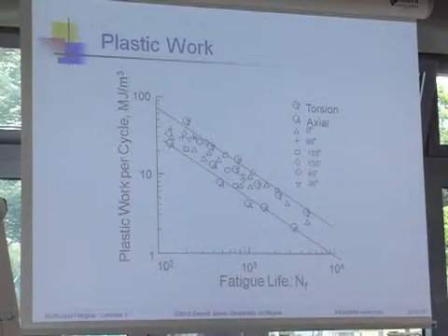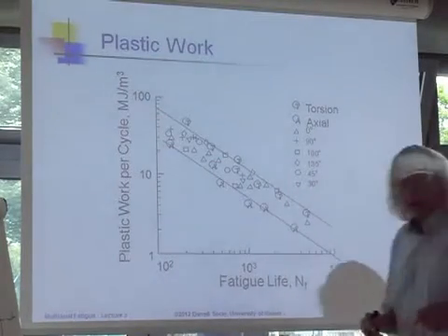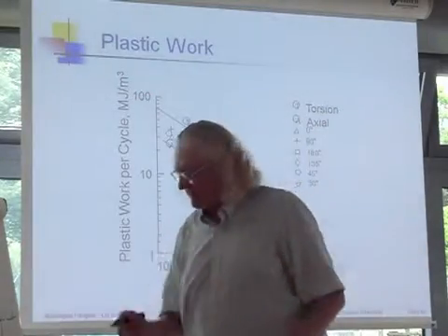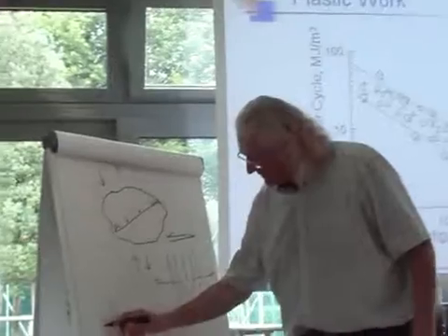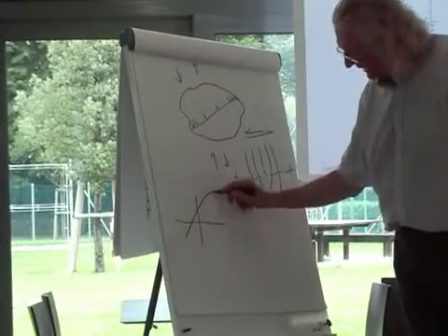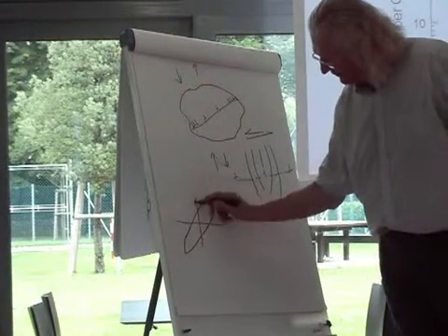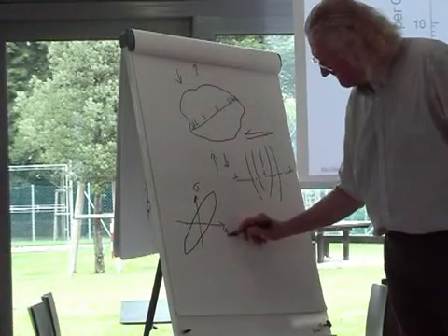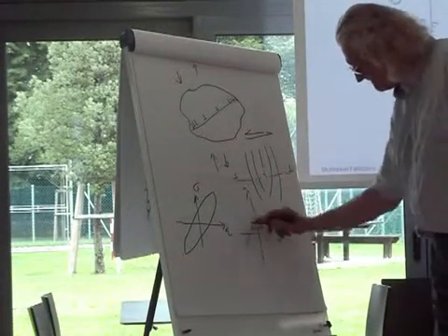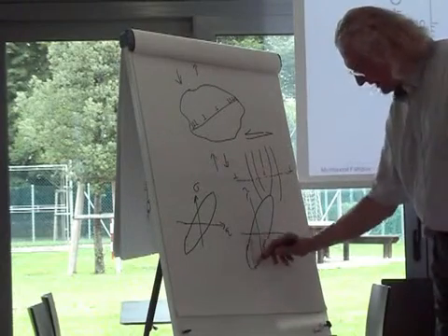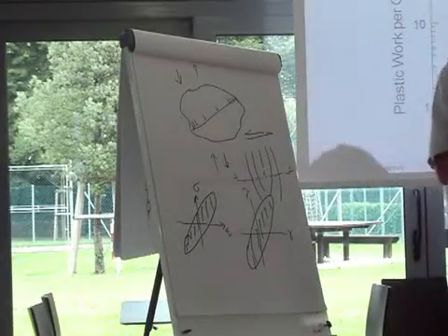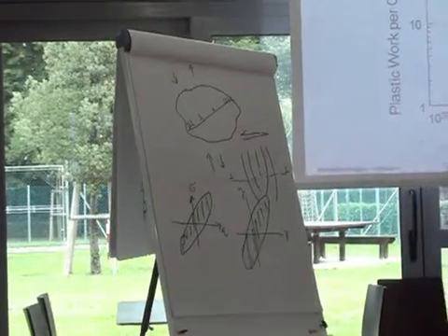And these are people that do things like calculate the energy. A bunch of energy models. And if you think about it, that's kind of attractive, right? So you get these really complicated hysteresis loops. So I'll draw a simple one, but I can look at the axial stress and axial strain, and I can look at the shear stress and shear strain, whatever it looks like, and just take the energy in here and add it to the energy in here and calculate the fatigue damage. And I can do that for as complicated a loop as I like.